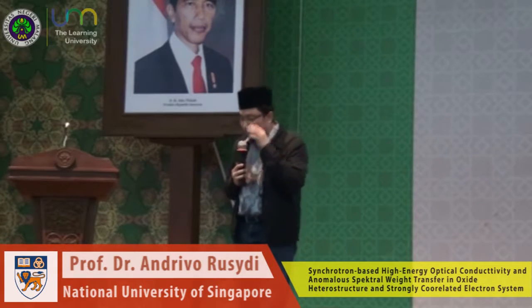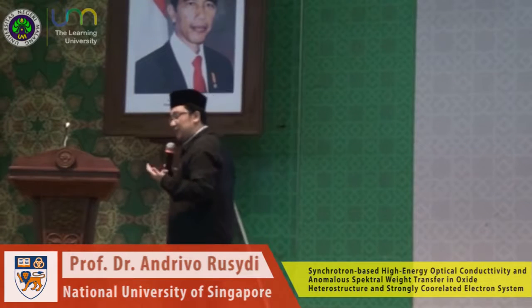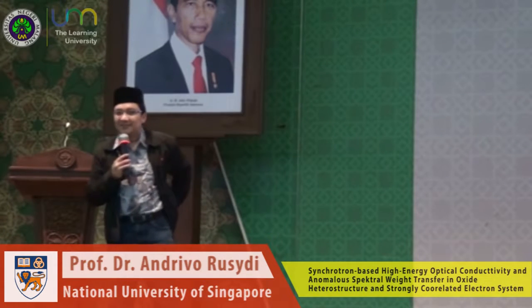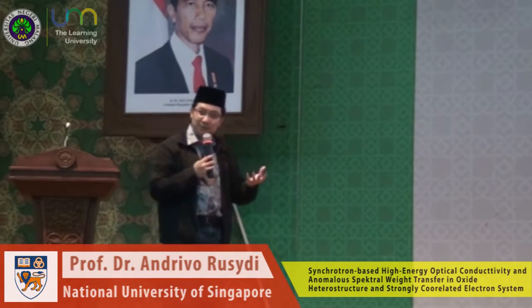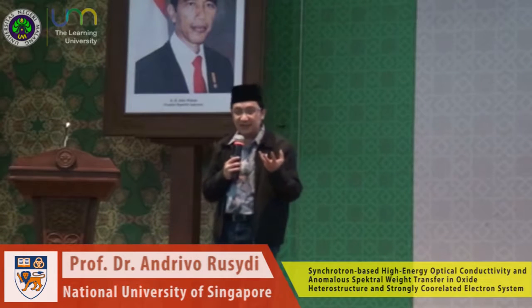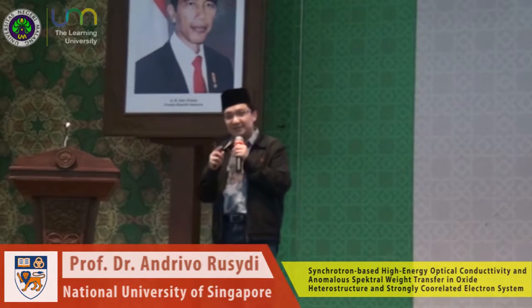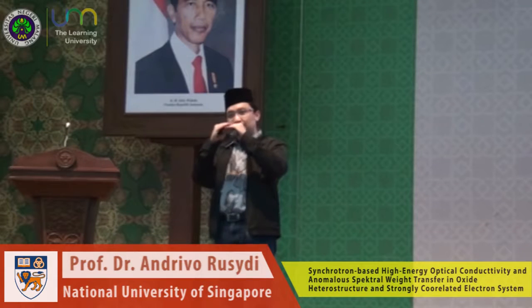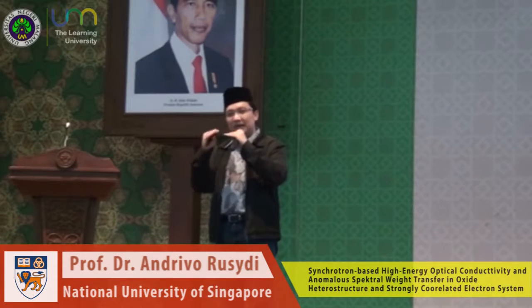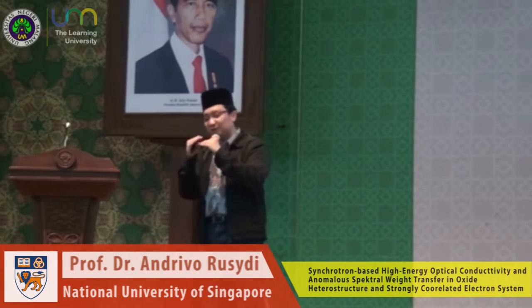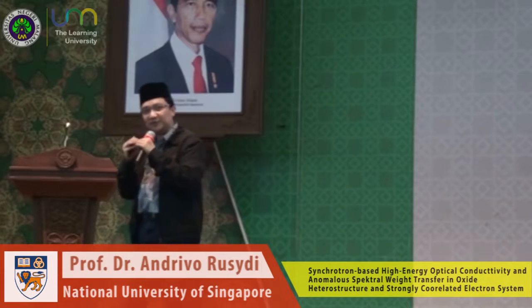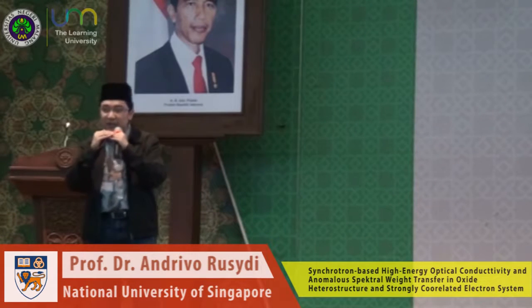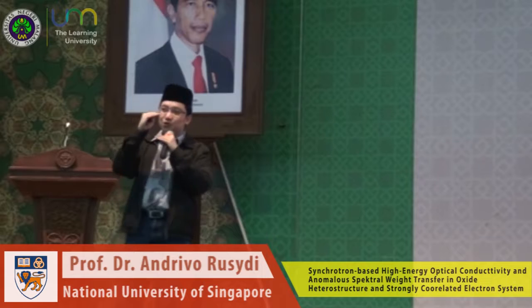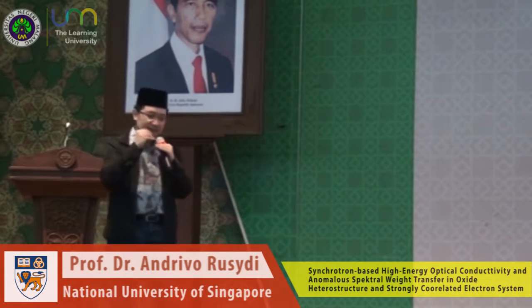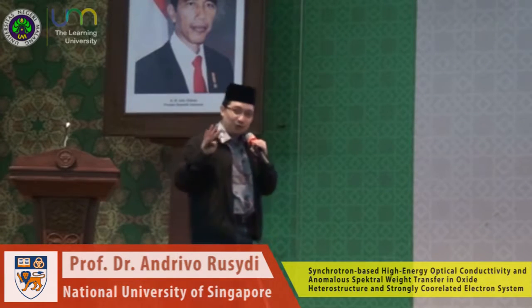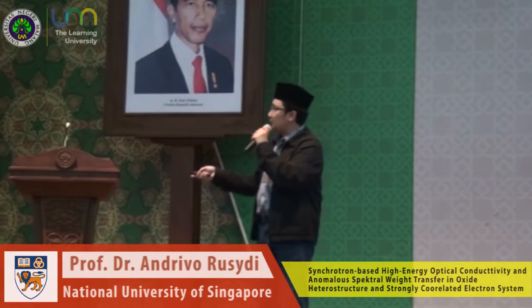So now you can really see that when you do physics, you really need to have good chemistry, because everything is related to stoichiometry, and you really need to understand that properly. Whatever you do, for instance if you make thin films, you really have to consider the surface before you think deeper about what happens at the interface. Even though the samples are very thick, the surface is still connected very nicely with the interface through this so-called charge transfer phenomenon.